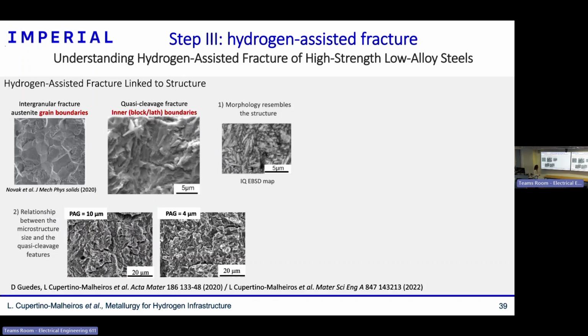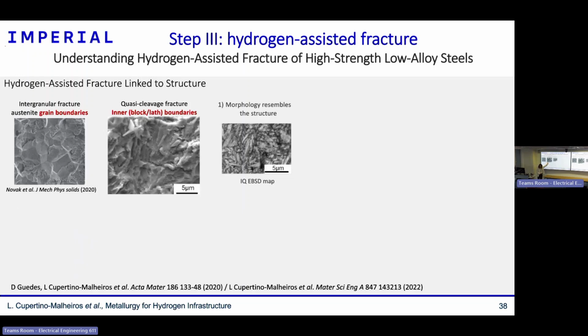Well, maybe what I said was misleading. What I said is that when you look at how these tempered martensitic steels were breaking, you don't think at first glance that this is related to grain boundary decohesion, because intergranular fracture, as shown also in the work of my PhD for nickel, usually has these features here that are equiaxed grains. However, in that case, it looked like the grain structure of a tempered martensitic steel that has lots of inner boundaries is breaking. So it's more pointing to interfaces breaking than the influence of dislocations itself, those results, yeah.